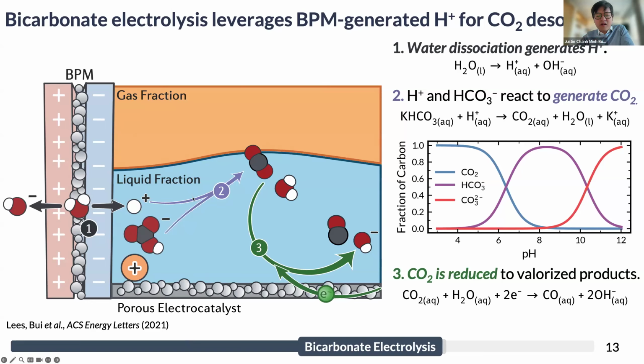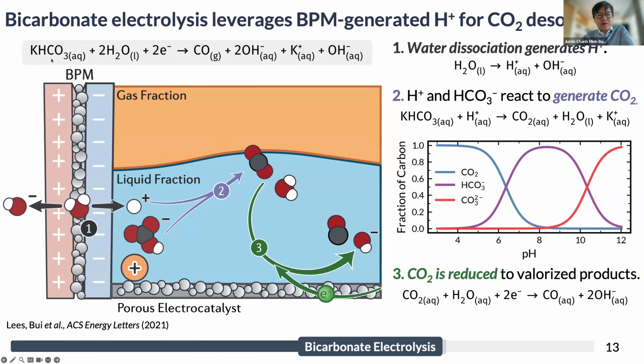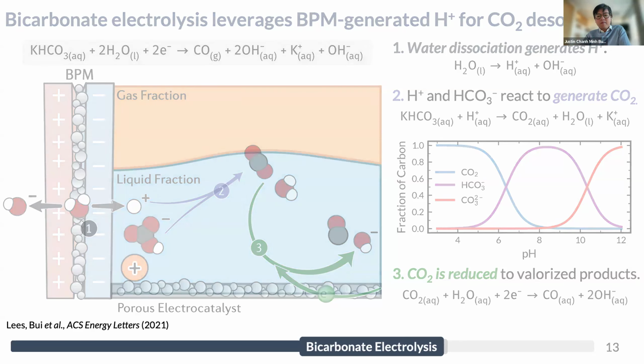And this was work that we did with Curtis Berlinguette's group at UBC. We were trying to really understand the system of not just carbon capture, but also sequential conversion of the captured and desorbed carbon within a single system. And so you get this really nice net reaction where you can take a carbon capture sorbent and then, using the bipolar membrane water dissociation and that silver catalyst, directly go to CO gas, which is a very value-added product for downstream Fischer-Tropsch, making plastics and fuels.